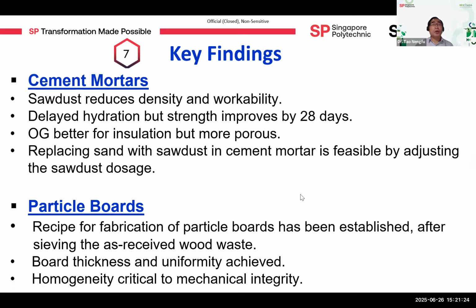The key findings from this project for cement mortars: sawdust reduced density and workability and delayed hydration, but strength improves by 28 days. OG is better for insulation, but more porous. Replacing sand with sawdust in cement mortar is feasible, but adjusting the sawdust dosage is key. For particle boards, a recipe for fabrication has been established after sieving the as-received wood waste. Board thickness and uniformity can be achieved. Homogeneity is critical to mechanical integrity.